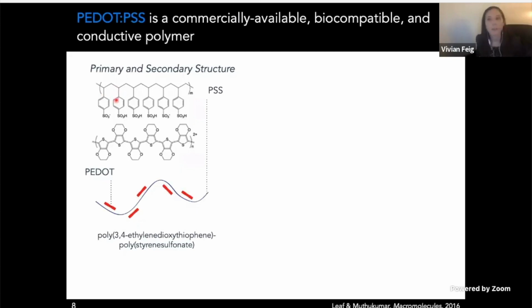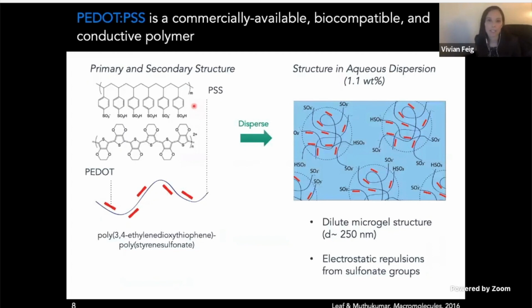And PEDOT:PSS is actually this two-component system where PEDOT here is the conjugated polymer, which, because it has alternating double bonds along its backbone, can actually transmit electrical charges. And then it's complexed with PSS, which acts both as a dopant for the PEDOT and as a way to disperse this in water. So the PEDOT:PSS that you can typically purchase from vendors is usually an aqueous dispersion of about 1 to 2 weight% of the polymer in water.